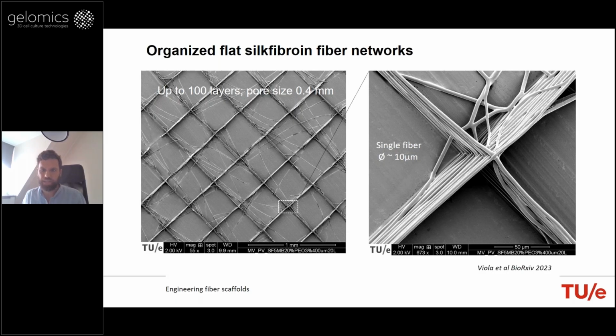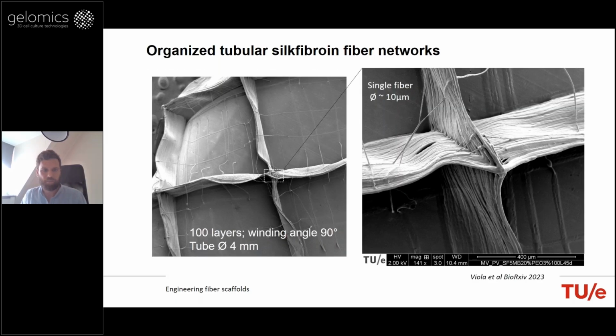up to 100 layers, and we could also achieve a tubular-shaped construct with the same layers, in this case tubes with a 4 millimeter inner diameter, and again 100 layers stacked down on top of each other. And here we look at winding angle, basically the angle between the printed walls of 90 degrees.